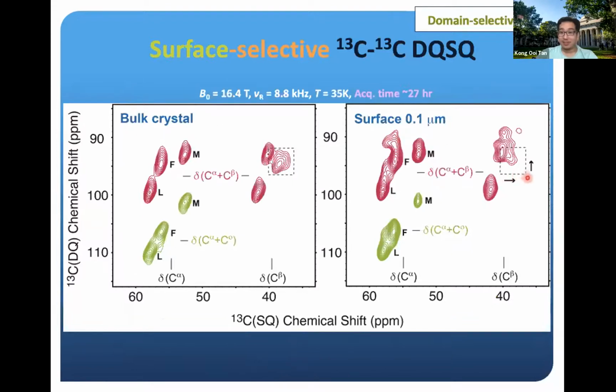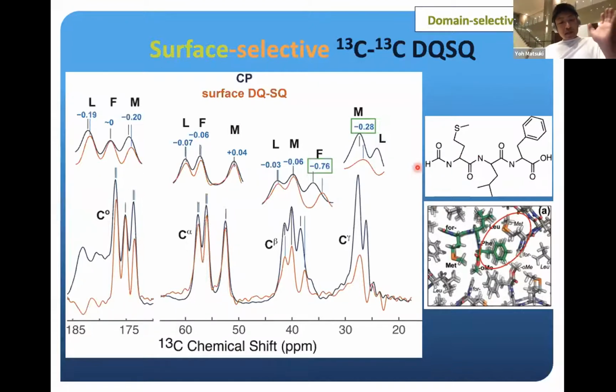The first thing we noticed is this slight peak shift and broadening for phenylalanine here. So we wanted to more closely compare the exact peak locations in the 1D data set. This is looking at the first FID taken from this 2D surface-only data, shown in red, compared with the regular CP in black. If you look at this blown up peak top here, it is pretty evident that peaks are shifting, especially the sidechain M and F here. They are closely packed in the crystal lattice, by the way.